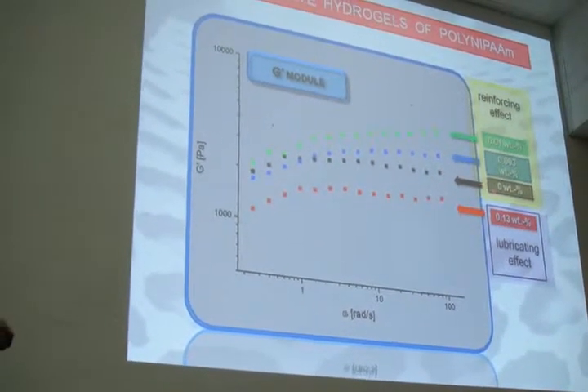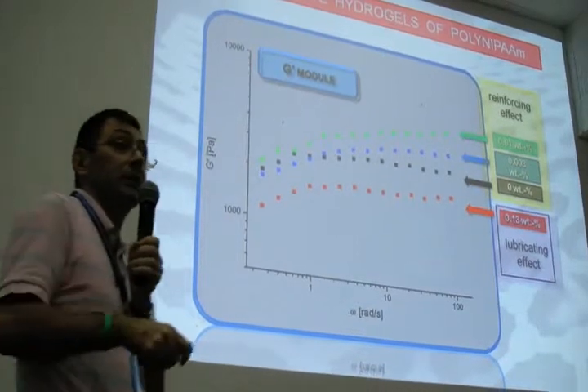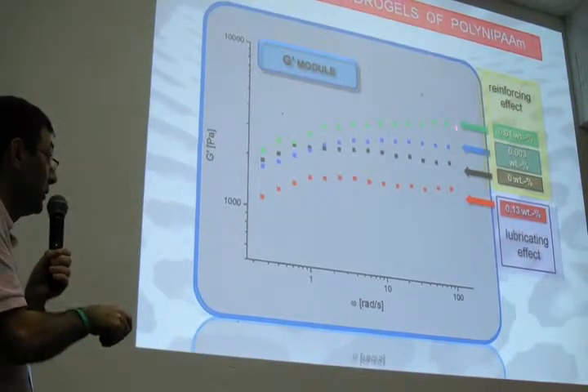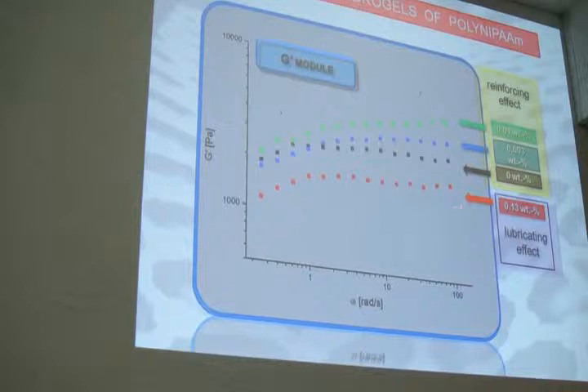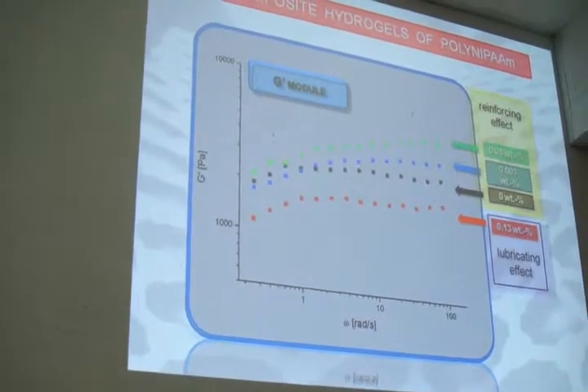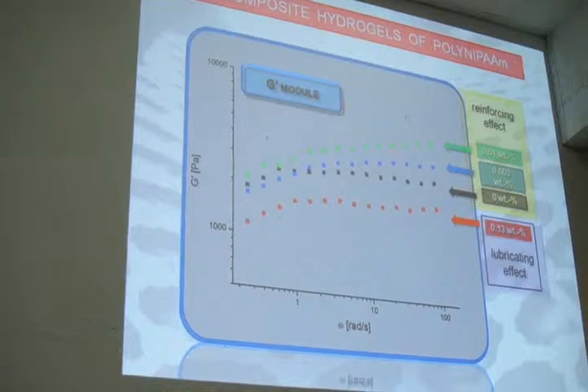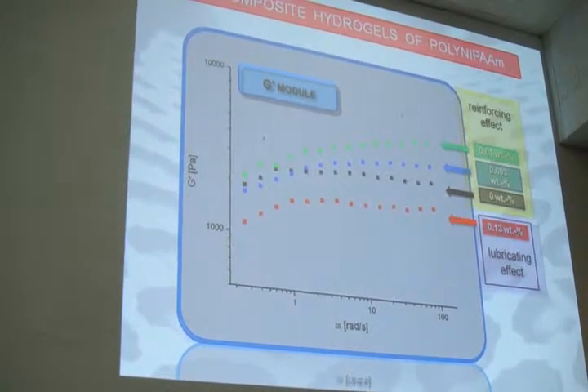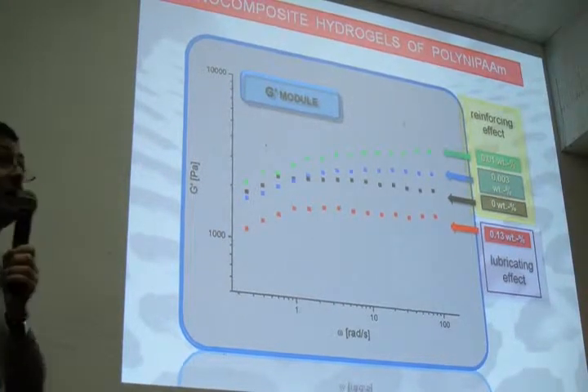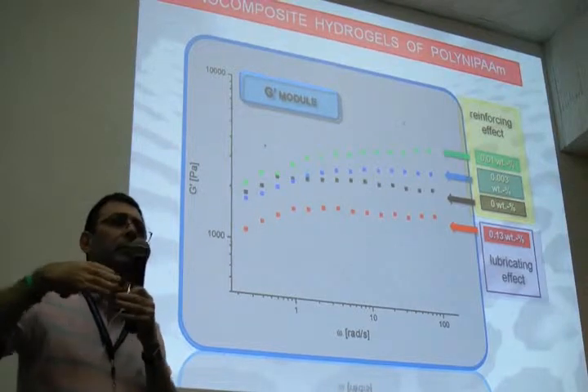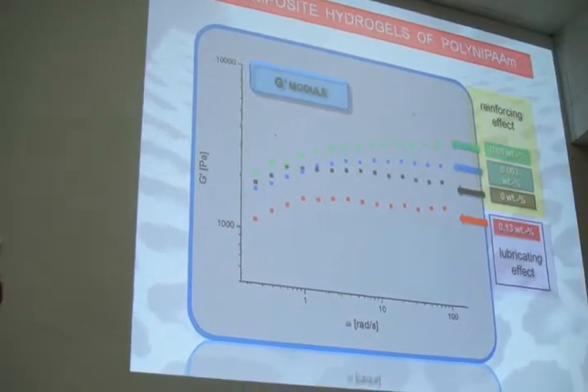What about the mechanical properties? The black squares are again those of the neat polymer. You can see that if I increase the amount of graphene, I have an increase of the modulus, but this is true only up to a threshold value. After that threshold value, I have a decrease of the modulus, so the reinforcing effect now is a lubricating effect. And this is also another characteristic of many polymer nanocomposites containing graphene. This is probably due to the possibility of the layers moving like sliding doors, we can say, one over the other.